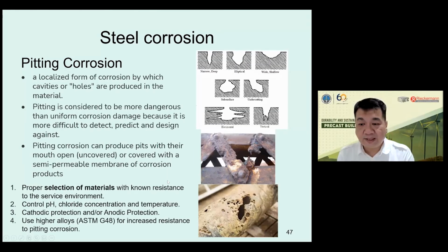And then the pitting corrosion, this is when localized corrosion occurs and causes damage deep inside the steel and causes holes. So there are many types of corrosion, and normally, due to the process of making the steel, I think the process is not quite uniform, and then you have some local conditions. So the material needs to be selected very well. And then there is also salt attack. So in a marine environment, we have chloride attacking the steel, which also causes pitting corrosion.